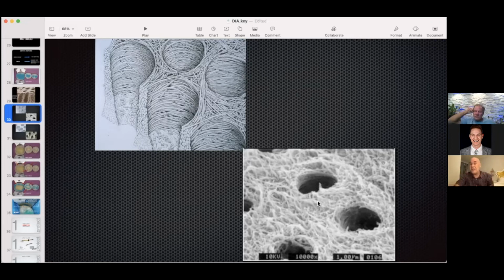What you need is for the adhesive to get into the intertubular dentin. As you go deep, your dentinal tubule diameter gets bigger, and there is a reduction in surface area for bonding, which is the intertubular dentin; the surface area gets smaller. That's why your bond strength goes down. Now, when you're down there, what you need to think about is protecting your pulp rather than bond strength, okay?